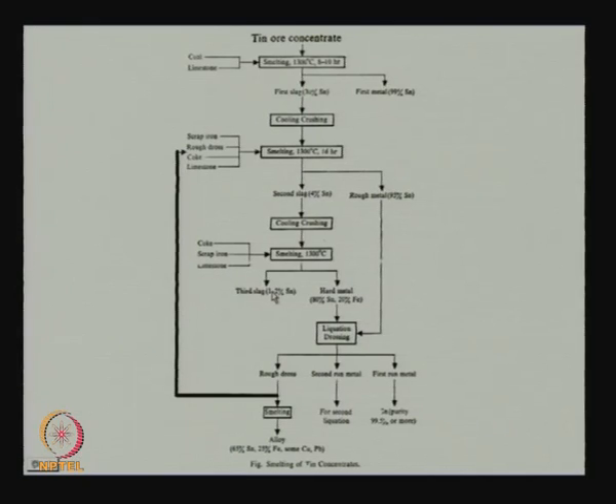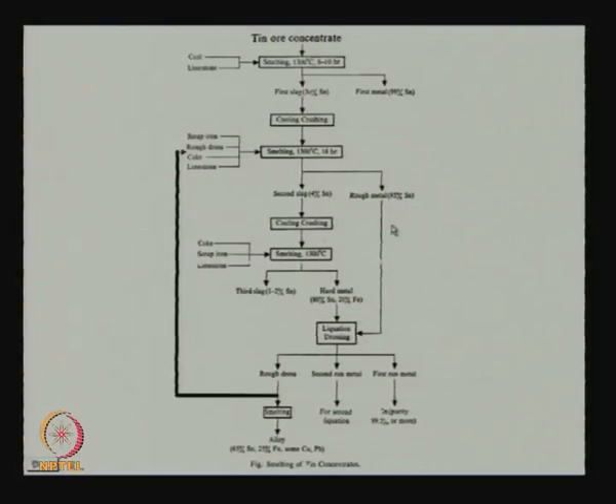So, you see how complicated the process becomes. The idea is to recover tin, also recover three kinds of tin, one which is fairly pure, the next step less pure, the third step not at all pure, but on the whole we have recovered almost 99% of the tin in the charge. Now, this rough metal, which is 92% tin, we mix with this third smelting metal, which is 80% tin and 20% iron, and it will go for liquation drossing.